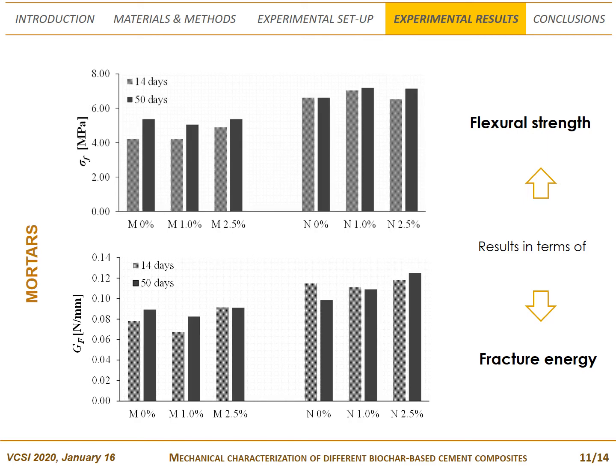The same mechanical properties were determined also for mortars. In this case, each batch was composed of three specimens. As regards mortar type M, it can be seen that the highest addition of biochar provides promising results, not only in terms of strength, but also in terms of toughness, especially at 14 days curing. Biochar tends indeed to produce beneficial effects on early age development of mechanical properties, since it acts as an accelerator that leads to early generation of more hydration products.